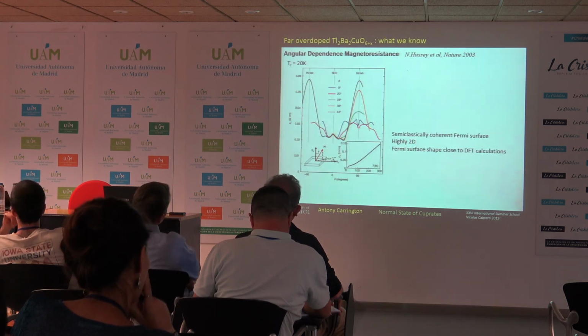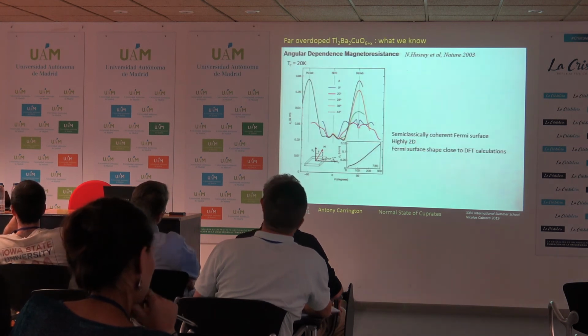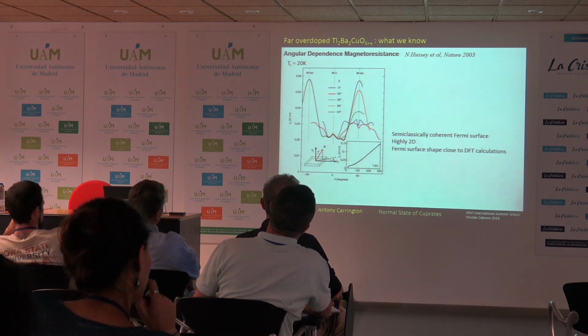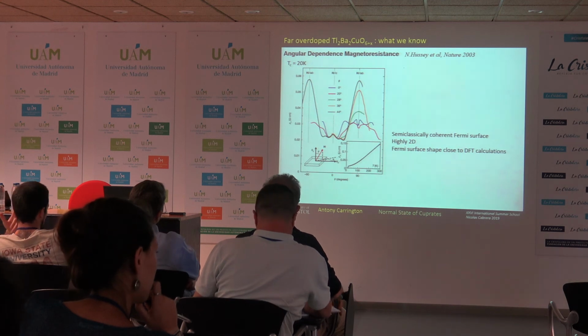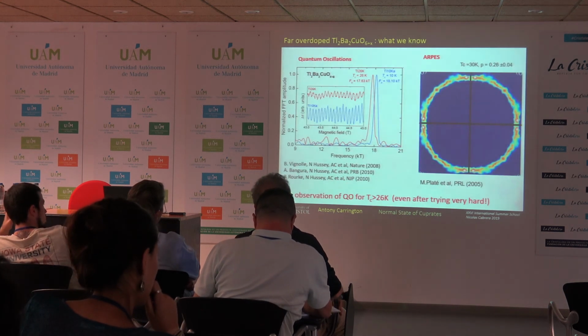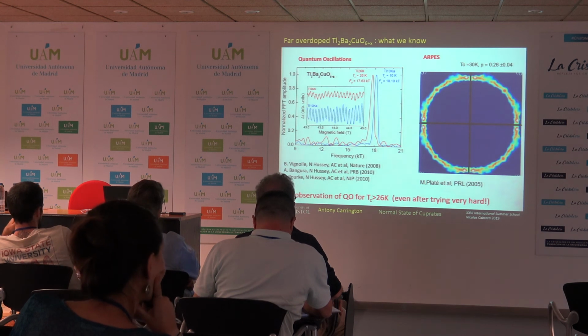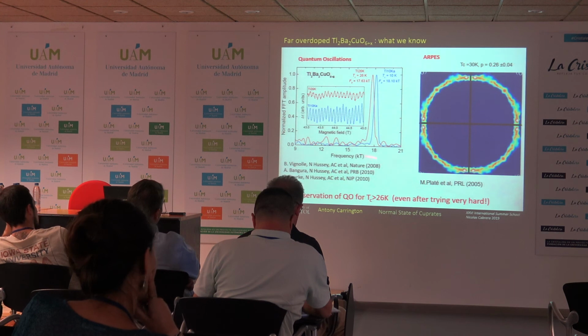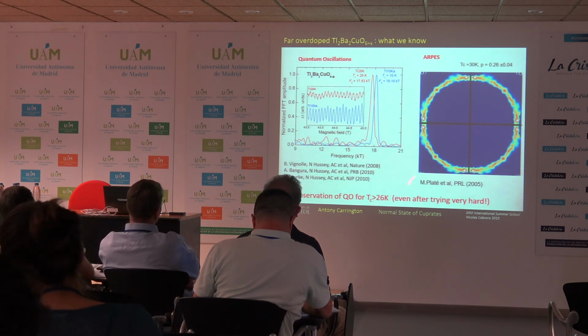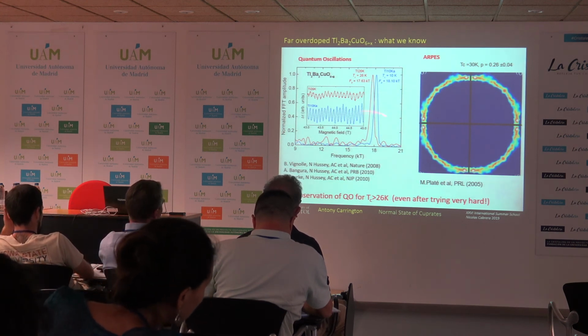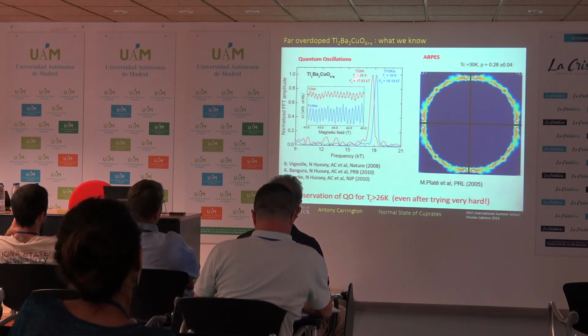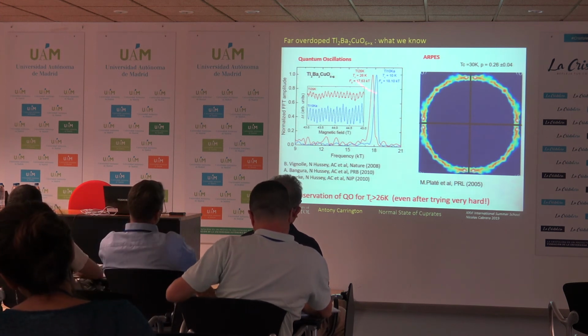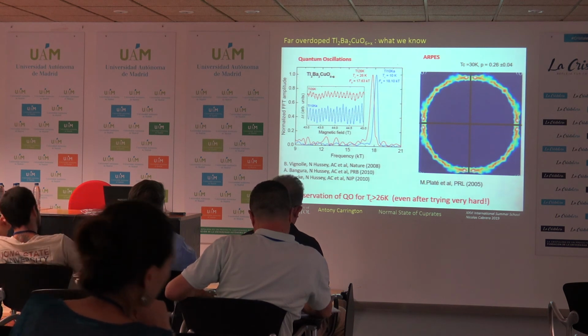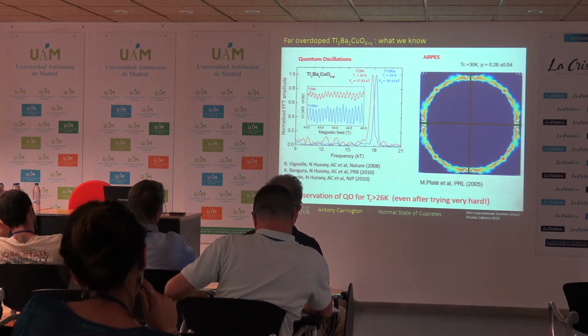Okay, so what do we know already? We know from analysing angle-dependent magnetoresistance roughly what the shape of the Fermi surface is, and in the interest of time, I'll zip on to quantum oscillations. So in 2008, we observed quantum oscillations for the first time, which showed that there is a large Fermi surface that essentially had the volume of what we'd expect, so 1 plus p volume.